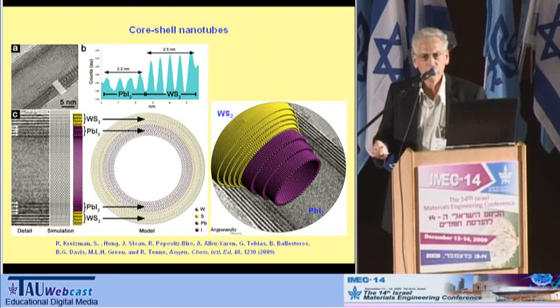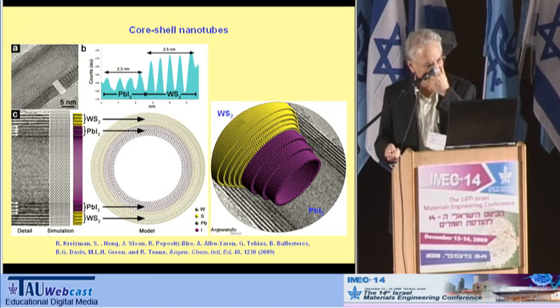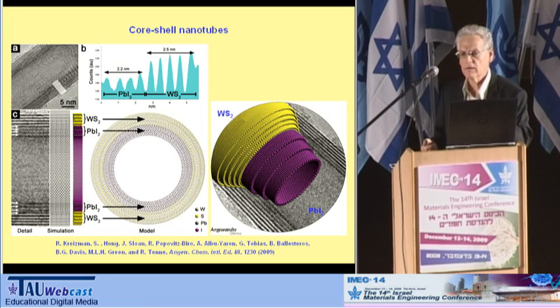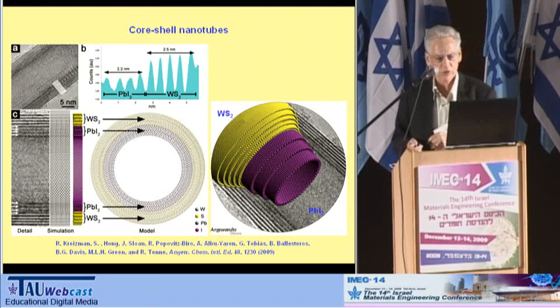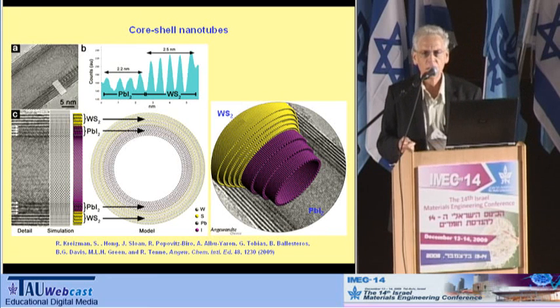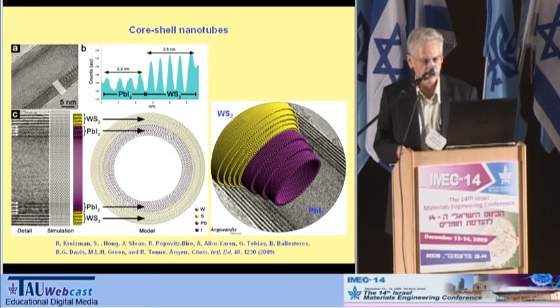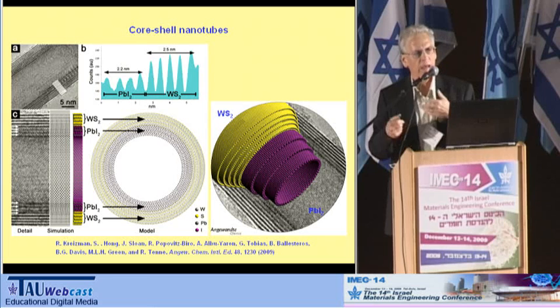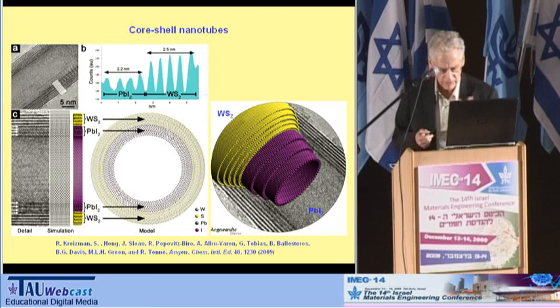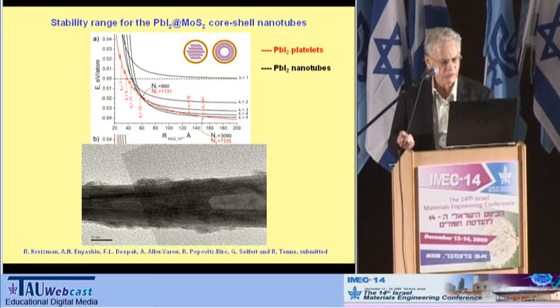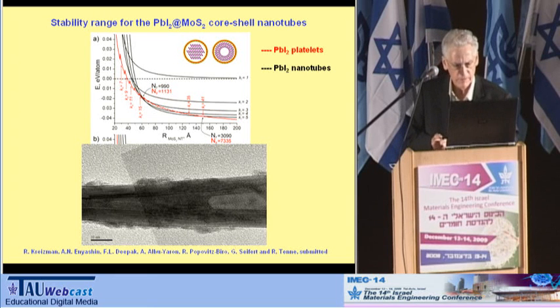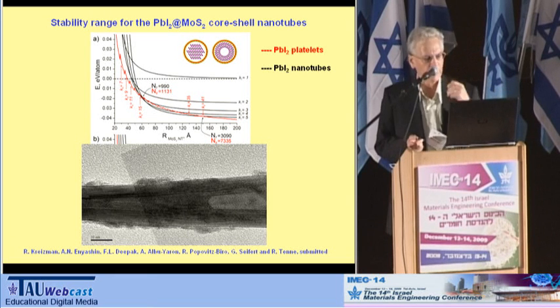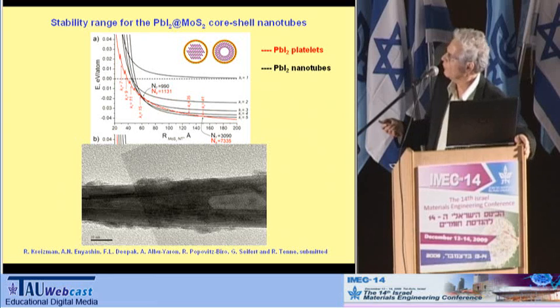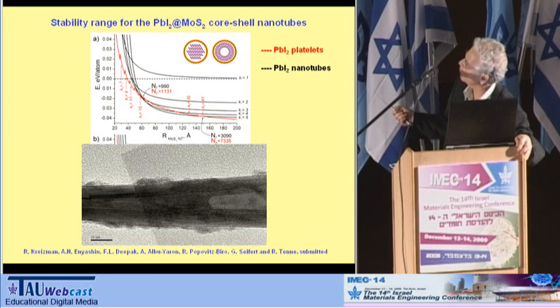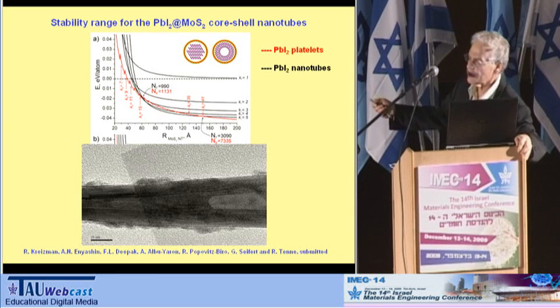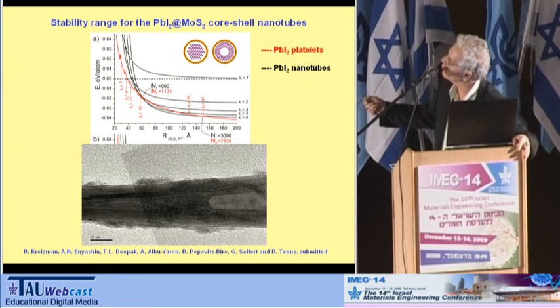So the idea here is that you can use the existing nanotubes of tungsten disulfide as template, and we can get now a lot of new nanotubes which we were not able to grow before due to their structure. And hopefully in the future we shall be able to synthesize them in larger quantities, study their properties, and see interesting applications for these nanoparticles. And a recent study that has been submitted now jointly with the group of Seifert shows very nicely the stability curve of the nanotubes versus the nanoplatelet.